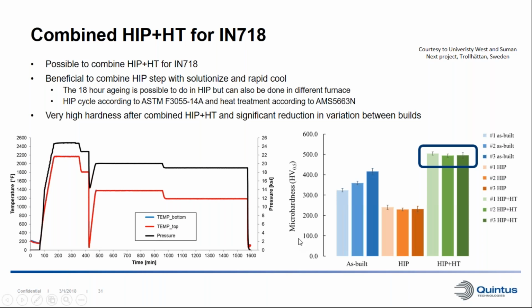On the right here, we show some results for some additive manufactured 718 that was processed with different cycles. So here we can see the hardness of the as-built material, and we can see that we have some variations in hardness depending on the different builds. When we HIP the material, we can reduce this scatter in the properties between the different builds, but we get a lower hardness. And this is for only HIPing, not heat treatment. When we combine the HIP and heat treatment in the HIP, we get a very high hardness and also very low scattering here, as we can see.